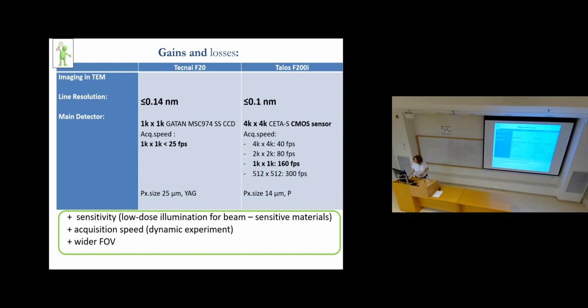So next, as a result of these advantages and the development of a more stable and more advanced electron optics, with the Talos we have improved resolution in the TEM mode. The numbers do not look that impressive because we already had 1.4 angstrom and now we will have better than 1 angstrom. But if we are talking about materials, it makes a sufficient difference. And on top of that, we have a much better detector for TEM acquisition.